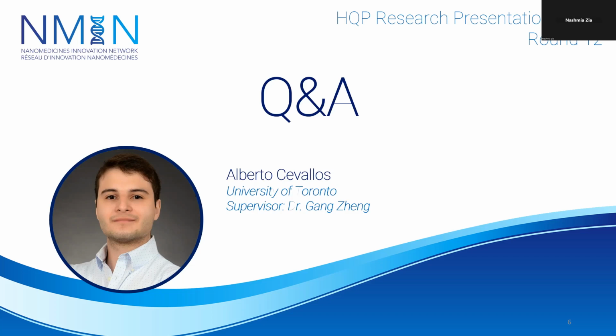Thanks for your question. So the chelation stability, I did it using liquid chromatography and mass spectrometry. What I would do is prepare the nanoparticle itself and characterize the spectrum of the nanoparticle immediately after the chelation. So I would see, once it's 100% chelated, how much of the chelated texaphyrin I can detect using mass spectrometry.